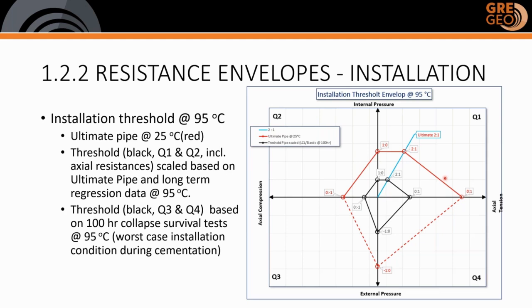Note that GRE is showing a degradation behavior. So this has to be taken into account, and that's why we used this approach. The ratio between the 2.1 ultimate point and this point is used as a scaling factor for the actual tensile point, the 0.1, and the actual compression point. The black -1.0 point is constructed using a 100-hour collapse survival test, and that is considered to be the worst case cementing operation.